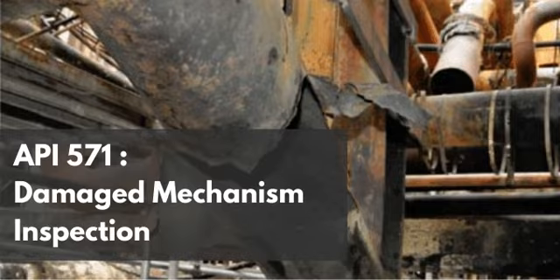Yes. If you put standard carbon steel in a high-temperature, high-pressure environment over years, the metal grains will slide past each other, the pipe will bulge, and eventually it will rupture. To stop that, we add molybdenum and chromium. This gives us the low alloy steels commonly encountered across refining operations. So we are talking about materials like carbon half moly, 1 1/4 chrome half moly, 2 1/4 chrome 1 moly, all the way up to 5 chrome and 9 chrome 1 moly.